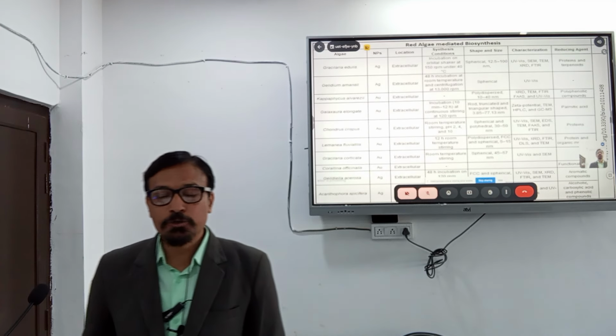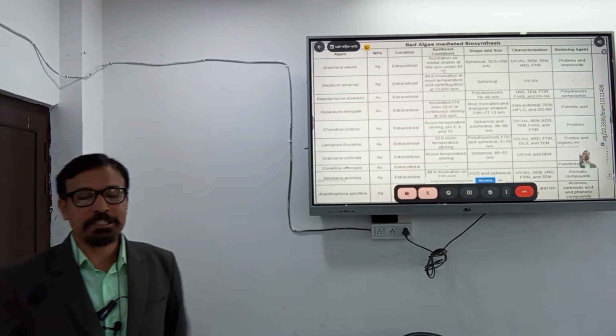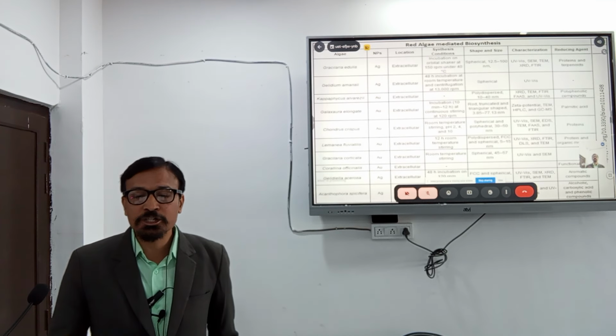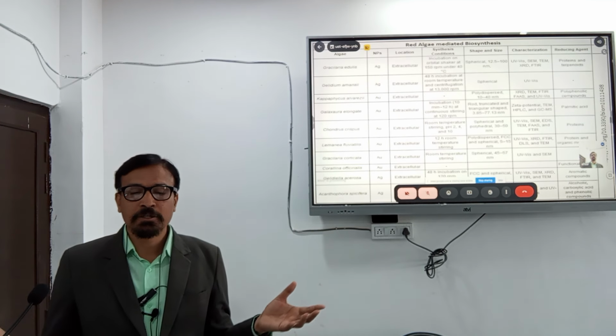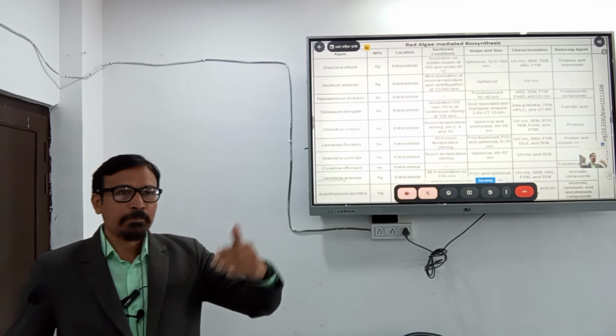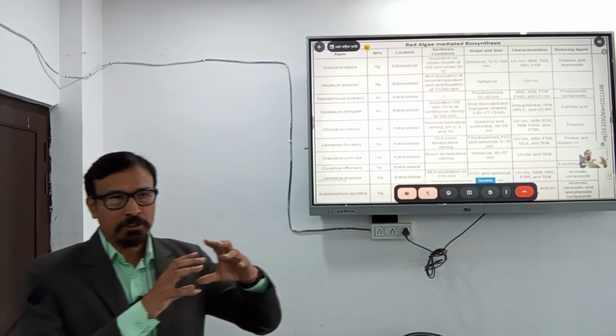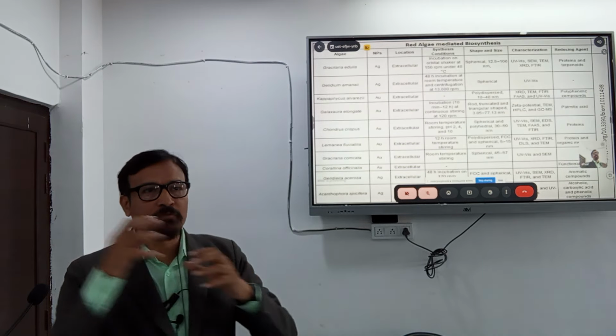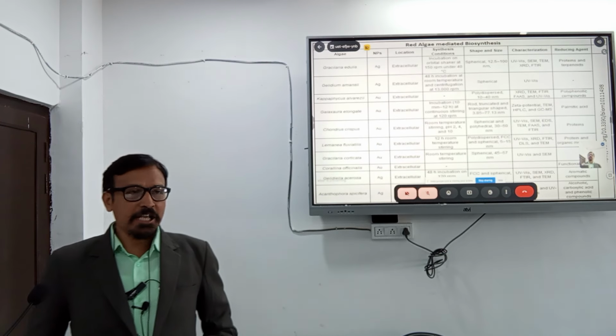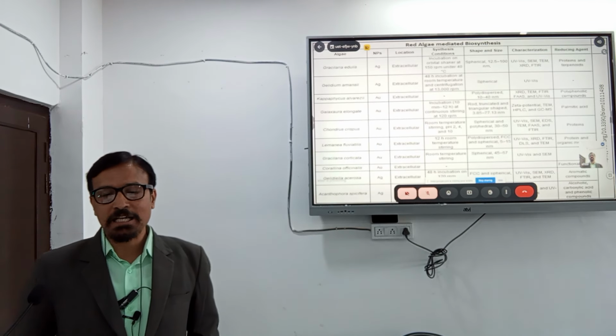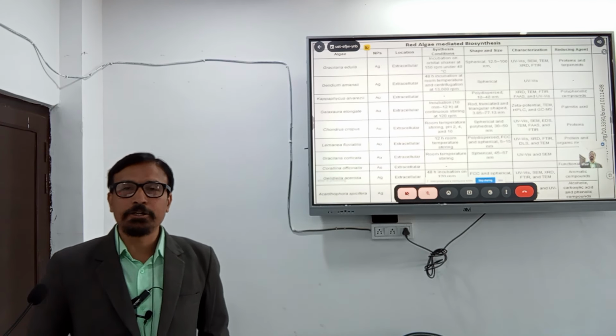Shape and size, the spherical size and characterization UV-vis, and next is the Kappaphycus algal-mediated, with which we can produce the gold nanoparticles. The location is extracellular, and the size and shape, that's polydispersed. That means that your sample will have nanoparticles of different sizes. And characterization of that can be done by XRD, TEM, FTIR, EDS and UV-vis.